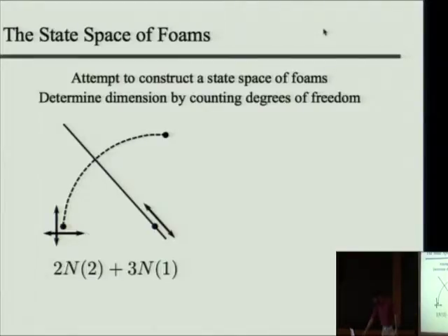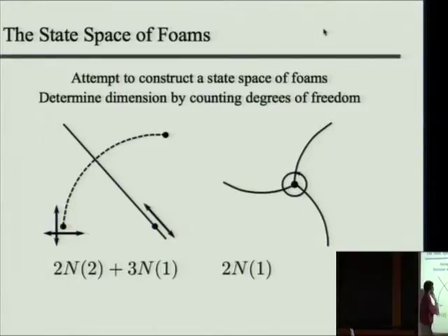How many constraints do we have? Suppose that we have a vertex with 3 edges coming into it. This is actually unphysical, because there's a torque associated with it, which would cause this whole system to rotate, and all these boundaries would become straight. Another way of expressing that is that the sum of the curvatures of the three boundaries around a vertex, taking the appropriate signs, must be 0. And in this case, they wouldn't be. So we have one constraint associated with the curvatures around every one of the 2n vertices.